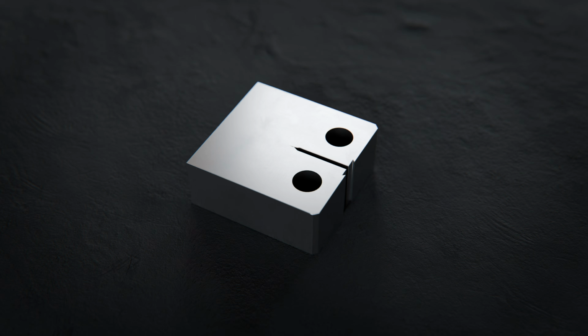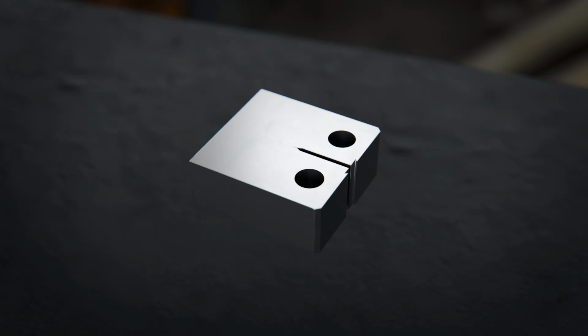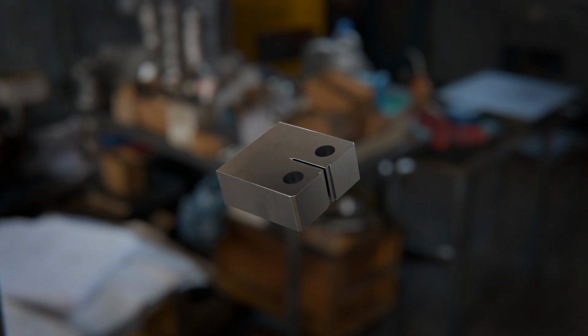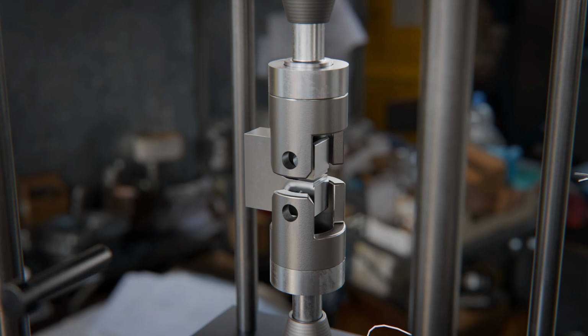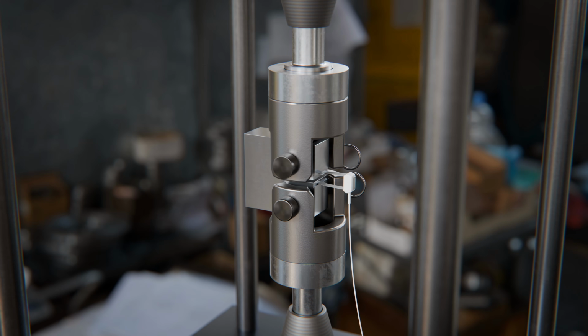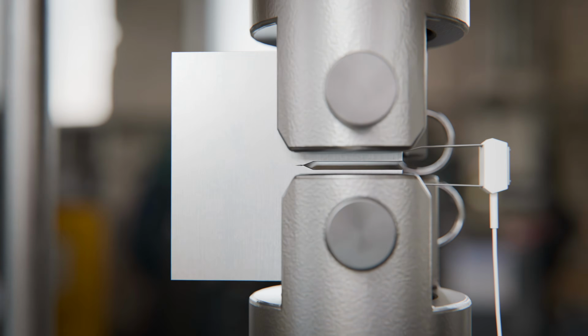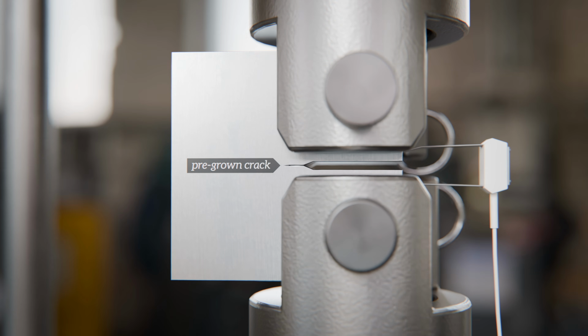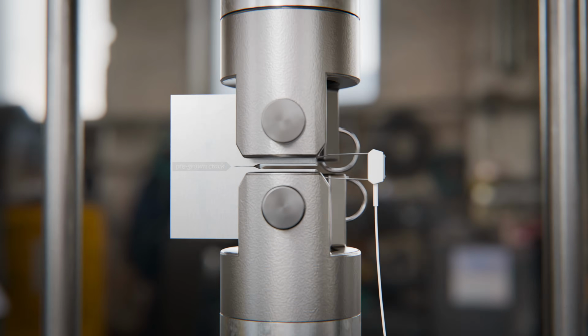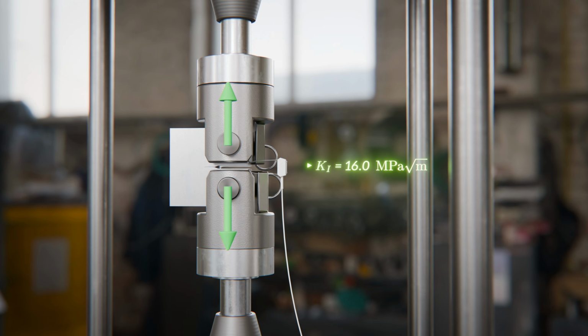The test involves machining a notch in a test specimen and applying cyclic loading to grow a fatigue crack in the notch to a specific length. Once the crack has reached the required size, the specimen is loaded to open the crack, while monitoring the applied force and specimen response. The value of K at which the crack begins to propagate unstably is recorded as the fracture toughness.